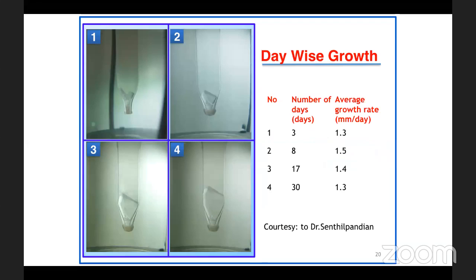So finally they will grow day by day. After 30 days, they have grown 1.3 millimeter per day. They have grown these crystals. So this is the simplest technique. One can grow any crystal to a big size, if you want big size crystals.